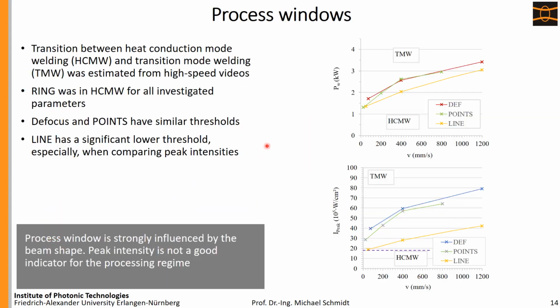So we had a look at the process windows, and what you can see here on the right side, in this diagram on the upper side, is the TMW, which is the transition mode welding, so the transition to keyholing, whereas here on the lower area we have the heat conduction mode welding. And the lines here represent for each intensity distribution the borderline between heat conduction mode and transition mode. And as you can see here, the line shape at first changes with the lowest powers to transition mode, whereas later on we get the point line, and then also the defocus changes.